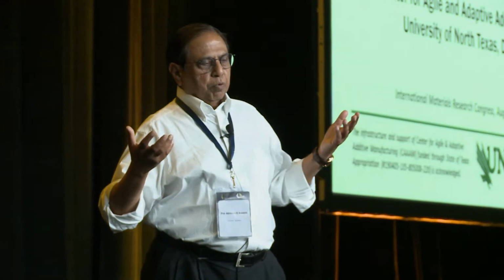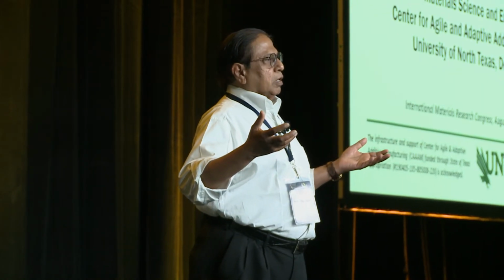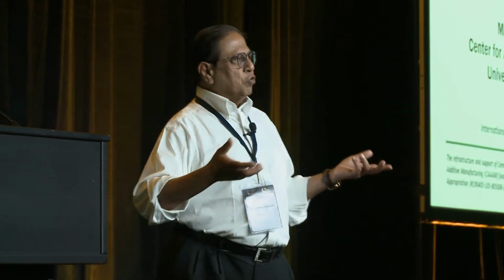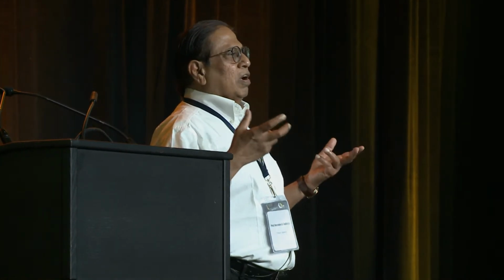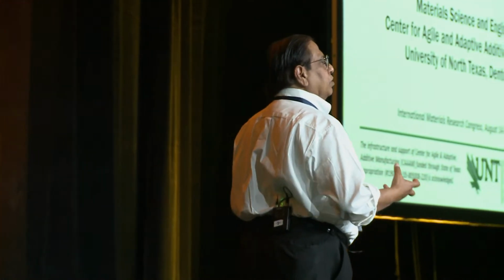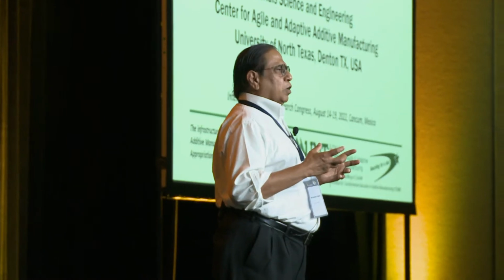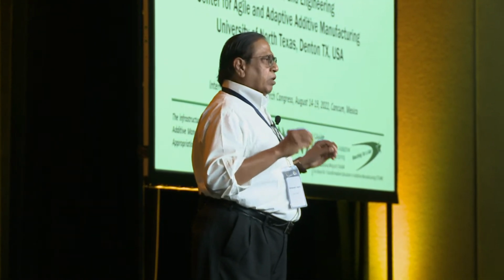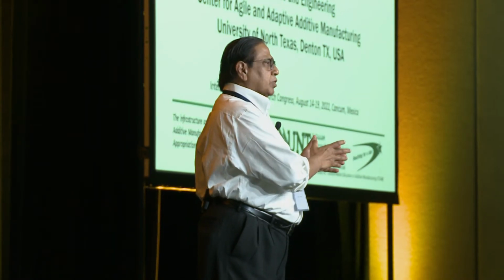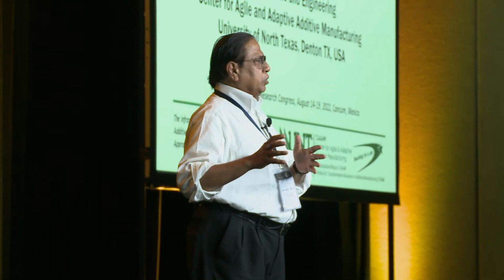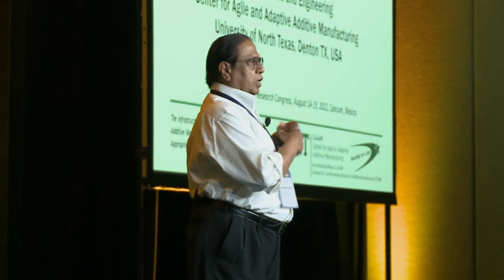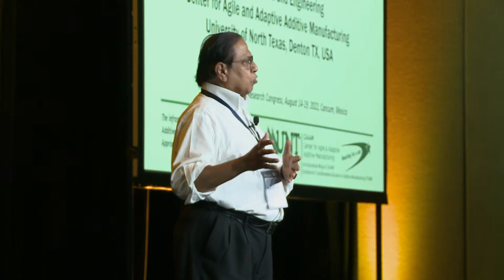The temperature attained in the processes is totally different. The kinetics of the process is different. What it means is that heating and cooling rates are different. And as you know, under different heating and cooling rates, material evolves with a different microstructure, different phase transitions, and so on. So this will tell you how important it is to know the thermokinetics of the process, and to really get control over additive manufacturing, one has to understand the manufacturing process and one has to understand the materials part of it. You cannot just live with the manufacturing process as an expert and not worry about the materials. You have to worry about it.